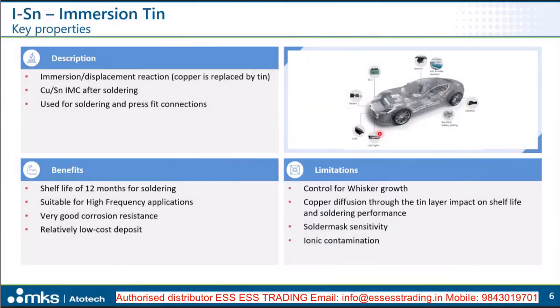A few words about immersion tin in general, which probably most of you know. Nevertheless, let me just get everybody on the same page. Immersion tin plating is a displacement reaction, so we dissolve copper during the deposition of the tin and create the tin layer on the copper directly. This means when the immersion tin layer is soldered, we form a copper tin IMC where the tin layer is completely dissolved into the solder. And immersion tin layers are typically used for soldering applications or press fit applications.